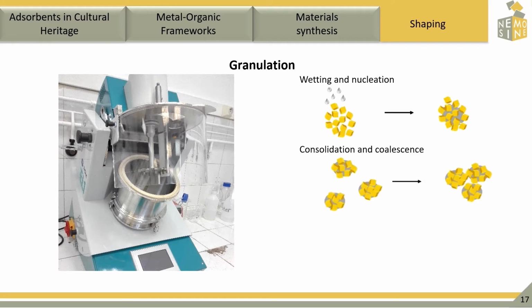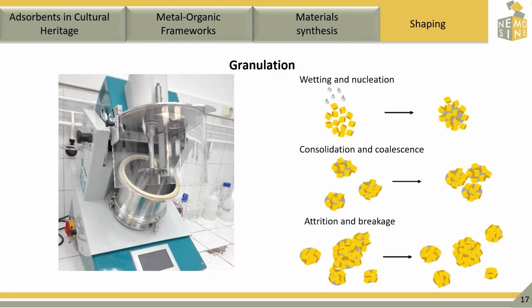Granulation processes can be characterized into wet and dry granulation. In the wet granulation that we use, a volatile solvent, for example water, is used to bind the powder particles into granules and then is removed by drying. However, if cohesion forces are not sufficient after drying, a binder can be added. The three general steps of granulation are wetting and nucleation, consolidation and coalescence, and attrition and breakage.